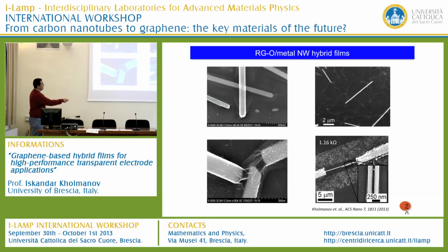But if you put the RGO, RGO can provide a two-dimensional platform for charge carriers through the metal nanowires. Moreover, you can see that this kind of nanowires can bridge the graphene platelets, decreasing the platelet junction resistance.